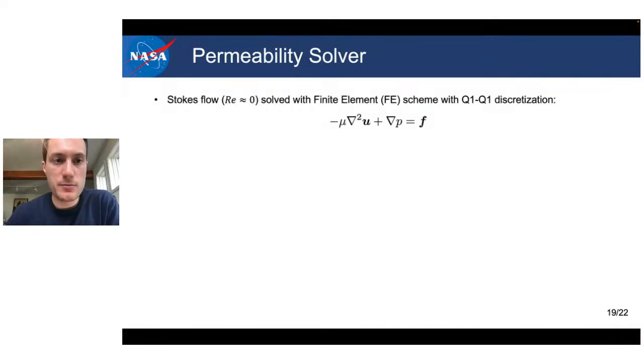So finally, the last solver that I'm going to talk about is the permeability, and this is actually chronological according to what was added last. This permeability solver solves Stokes flow, which basically is valid at very low Reynolds numbers. And we use a finite element scheme, which is based on a Q1 discretization, which basically means that we're using first order elements in both the velocity and the pressure. And so the governing equations can be written out like this for Stokes flow.